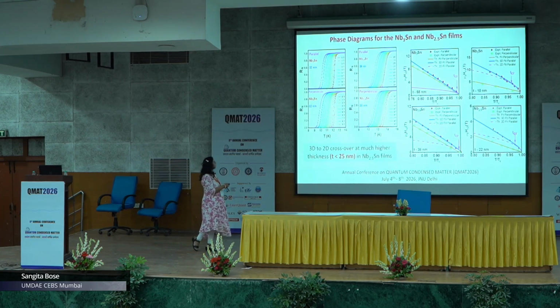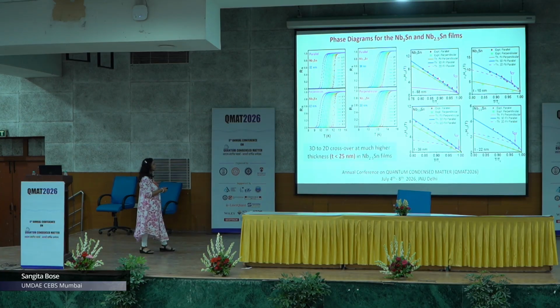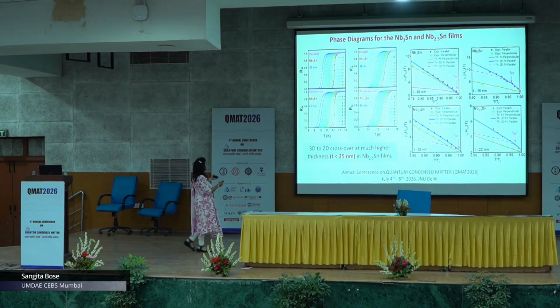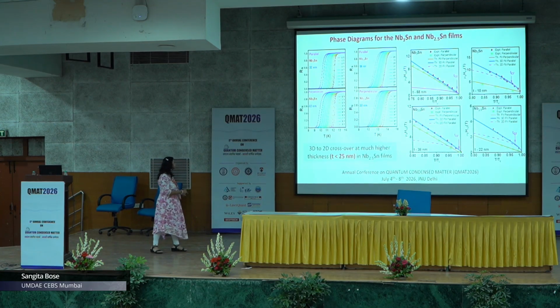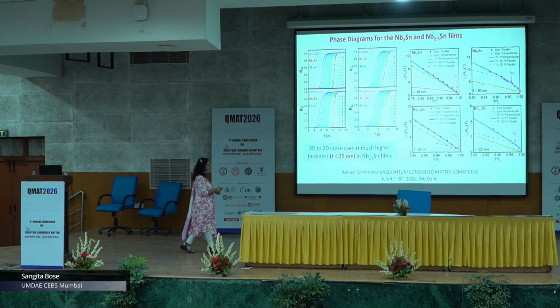Further on, we of course looked at the phase diagrams by doing the magnetoresistance measurements, as we reduce the film thickness in both the series. So, this is for the niobium 3 tin and this is for the niobium 2.5 tin. What we notice is the anisotropy between the parallel and the perpendicular. So, we measure the magnetoresistance for both the parallel and perpendicular orientation, and we try to look at the critical fields. Needless to say, it was not surprising that this anisotropy increases as you go to lower thicknesses. However, again the same thing, that this is happening at a much higher thickness for these niobium 2.5 tin systems.